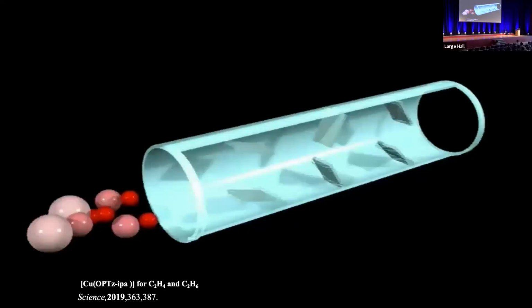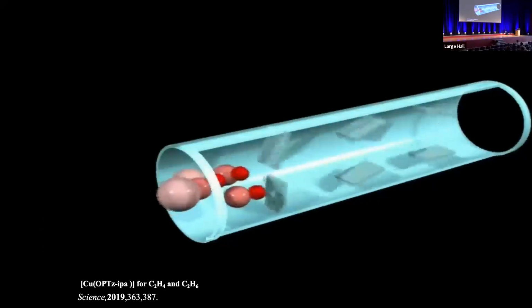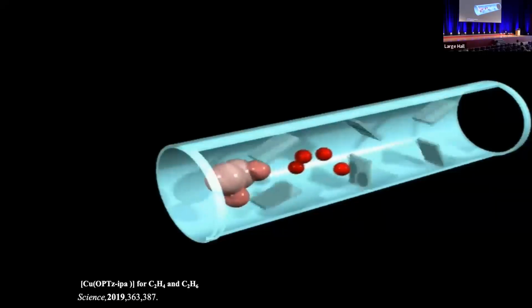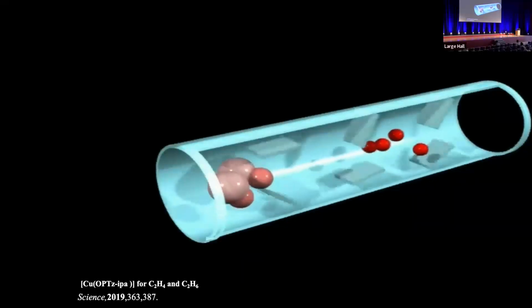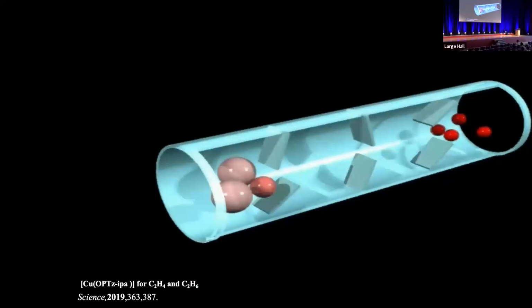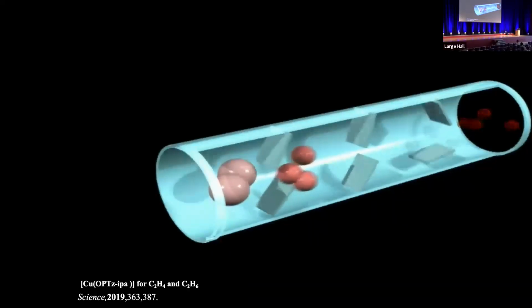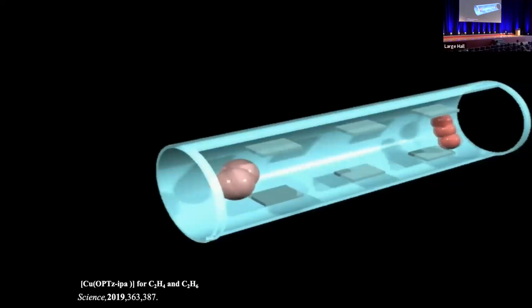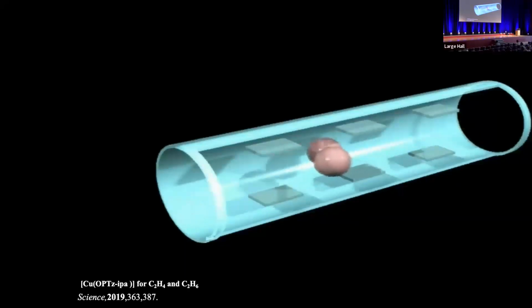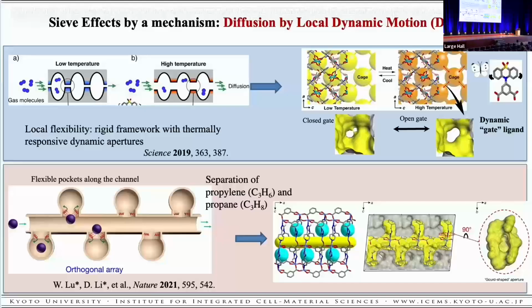In fact, mixture gases such as ethylene and ethane mixtures and oxygen and argon could be separated by the local motion of the MOF because of the different diffusion of the target molecules. Based on this idea, we developed the MOF 2 years ago that allows local motion to recognize the diffusion of guests and distinguish between those with very similar properties.